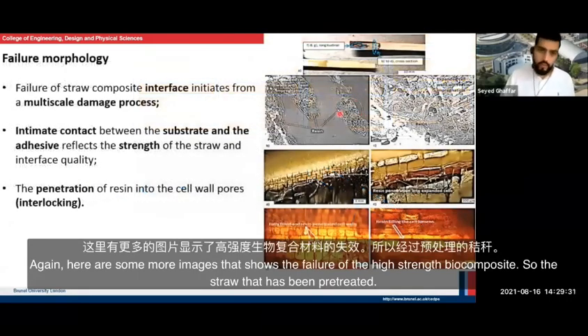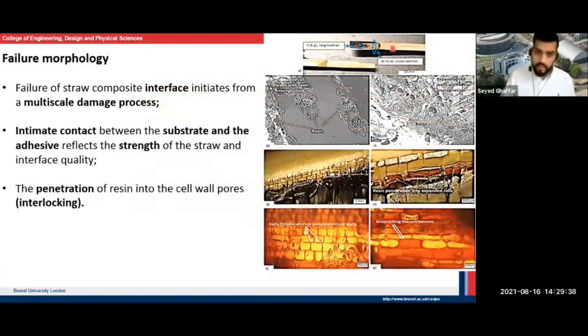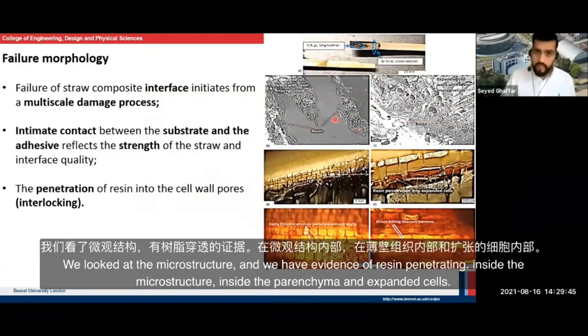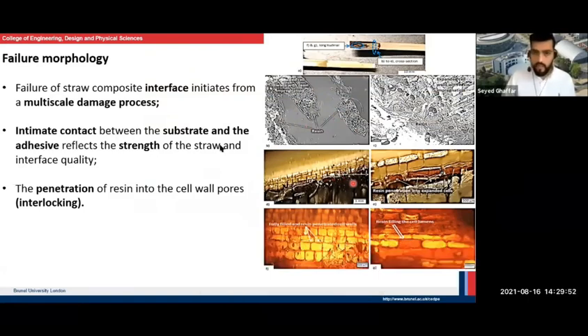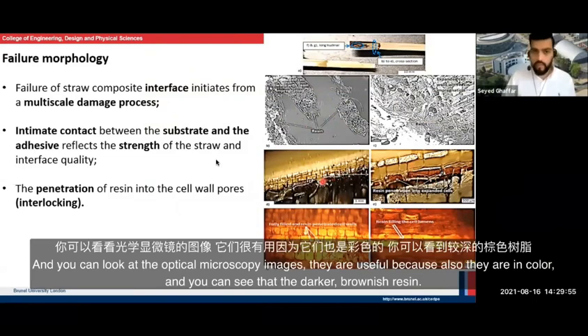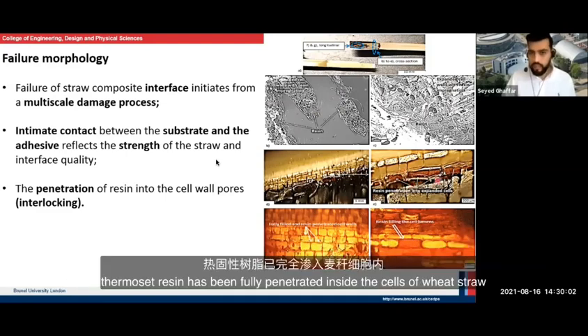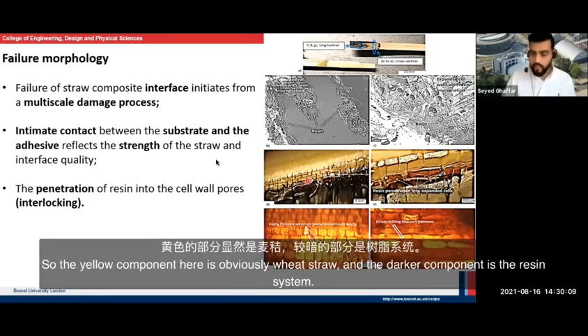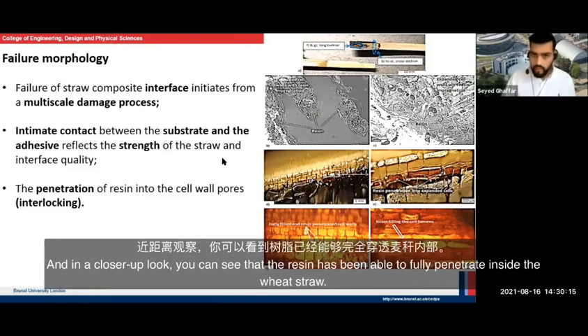Again, here are some more images that show the failure of a high strength biocomposite. So the straw that has been pre-treated, we have evidence after the failure. We looked at the microstructure, and we have evidence of resin penetrating inside the microstructure, inside the parenchyma and the expanded cells. And you can look at the optical microscopy images. They are useful because obviously they are in color, and you can see that the darker brownish resin, thermoset resin, has been fully penetrated inside the cells of wheat straw. So the yellow component here is obviously wheat straw, and the darker component is the resin system. And in a closer up look, you can see that the resin has been able to fully penetrate inside the straw.